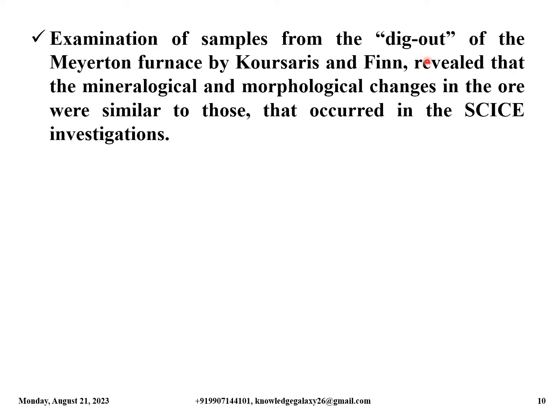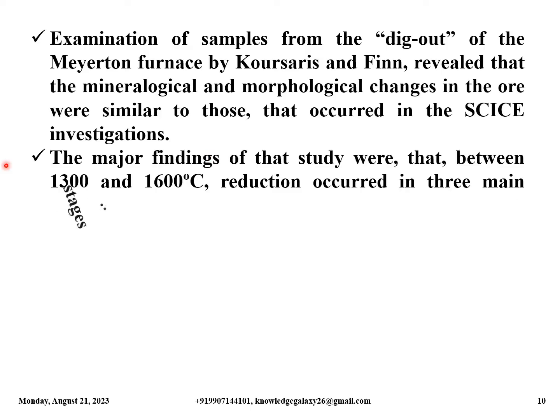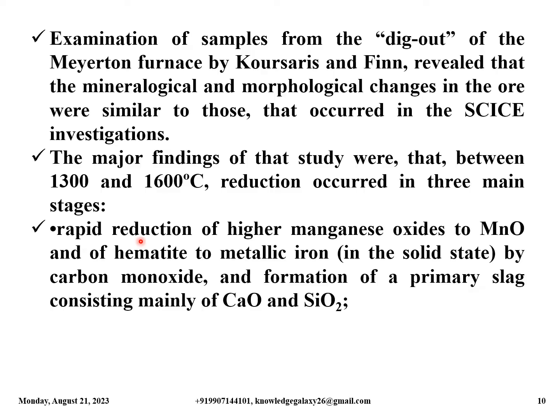Examination of samples from the dig out of the Meyerton furnace by Koursaris and Finn revealed that the mineralogical and morphological changes in the ore were similar to those that occurred in the SCICE investigations. The major findings of that study were that between 1300 and 1600 degrees Celsius, reduction occurred in 3 main stages. First, rapid reduction of higher manganese oxides to MnO and the hematite to metallic iron in the solid state by carbon monoxide, and formation of a primary slag consisting mainly of CaO and SiO2.